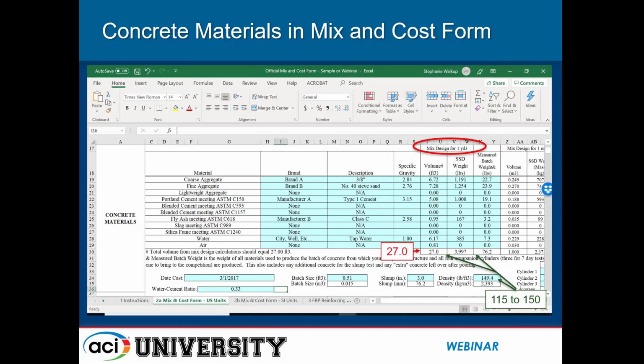In addition, if you take the saturated surface dry weight of all of your materials and divide that by the volume of 27 cubic feet, you will get the density of your concrete in pounds per cubic foot. This value should range between 115 pounds per cubic foot for a lightweight concrete to around 145 to 150 pounds per cubic foot for a normal weight concrete. If your density is not in this range, this is a flag to somebody reviewing your mix and cost form.